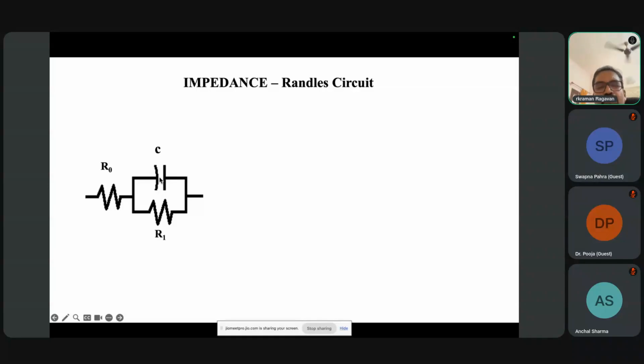So every electrode-electrolyte interface, independent of whether it is doing a Faradaic reaction or not. What is a Faradaic reaction? A Faradaic reaction is nothing but the charge transfer reaction. For example, in the lithium battery case that we discussed, what is the Faradaic reaction there? Where cobalt was switching between 3+ and 4+. That was a Faradaic reaction. So this can be considered as a capacitance associated with that electrode-electrolyte interface, and the charge transfer reaction is giving you this resistance value here. And all these ions which are intercalating and deintercalating are coming through an electrolyte.